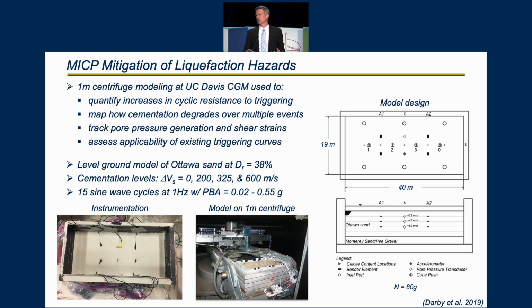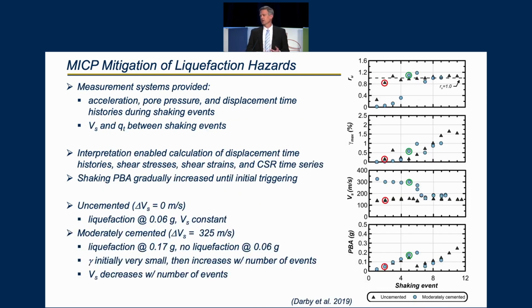There was a host of different tests performed, but we're just going to take a look at two today for simplicity. One being the uncemented case, or the existing ground conditions, and the second being for improvement to about 325 meters per second increase. The various measurement systems allowed us to make two types of observations. The first is the discrete sensors allowed us to monitor the performance during the shaking event. And the second is that the shear wave velocity and cone tip resistance could provide measures in between or after particular shaking events, much like we do with our case histories in the field.